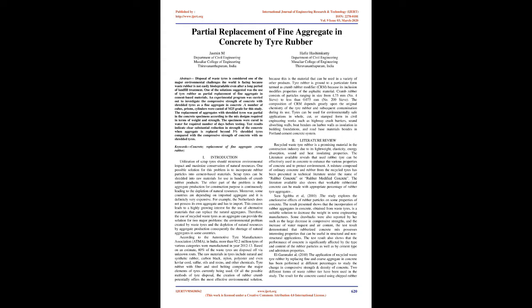Test results indicate a clear, substantial reduction in strength of the concrete when aggregate is replaced beyond 5% shredded tires, compared with the compressive strength of concrete with no shredded tires. Keywords: concrete, replacement of fine aggregate, scrap rubber.